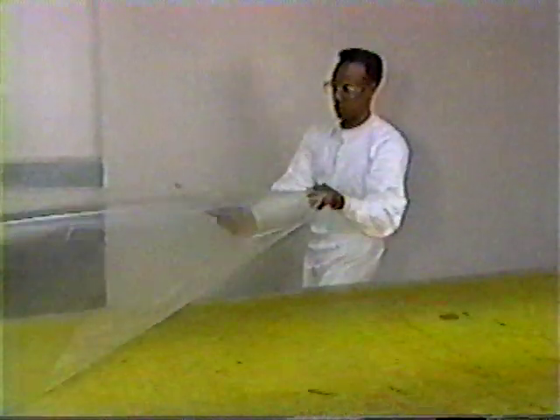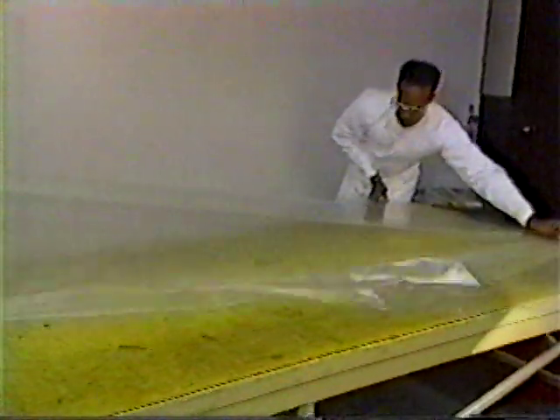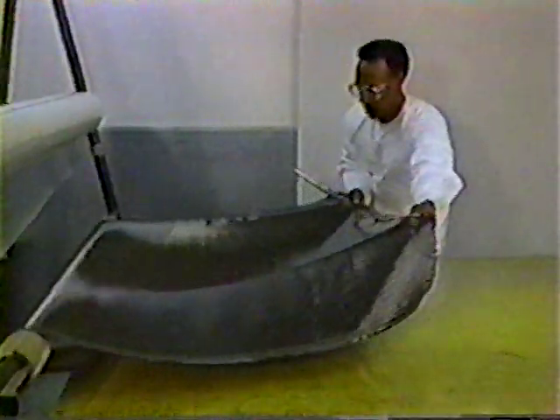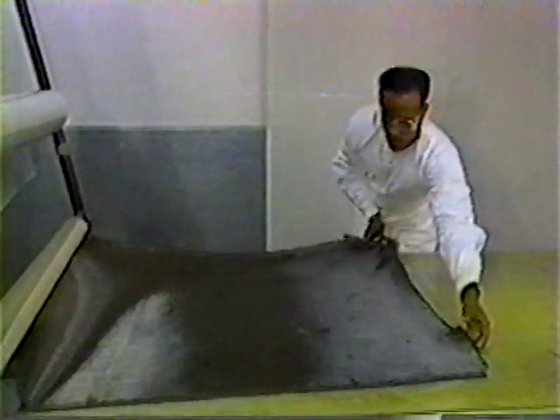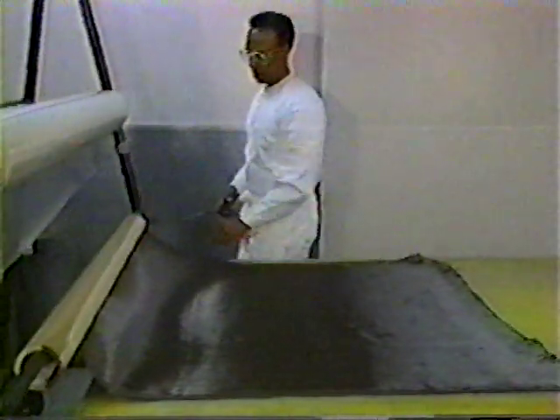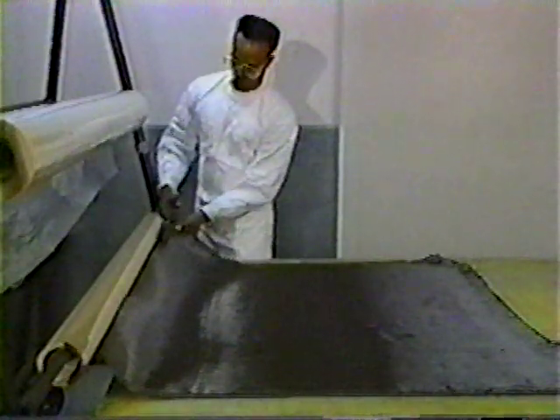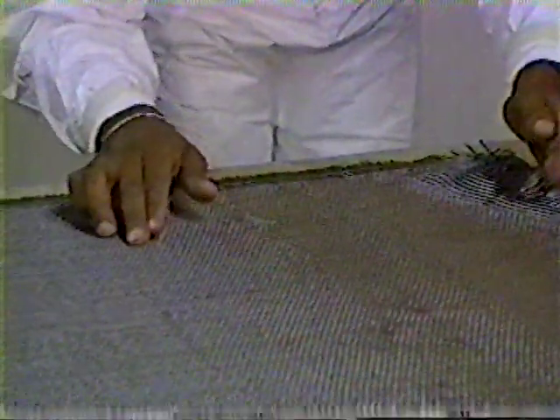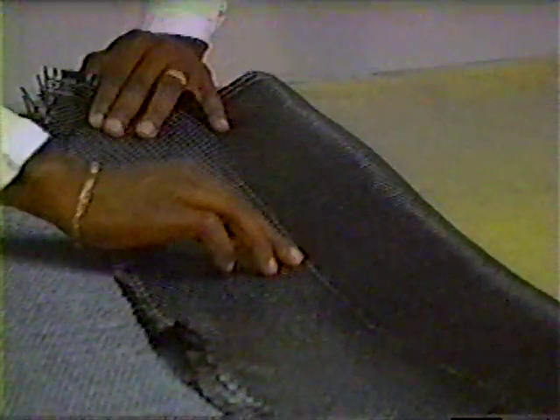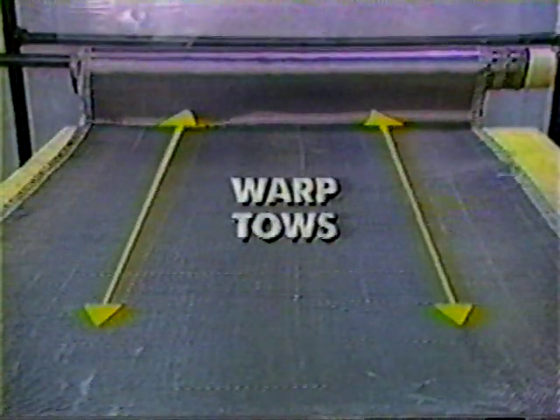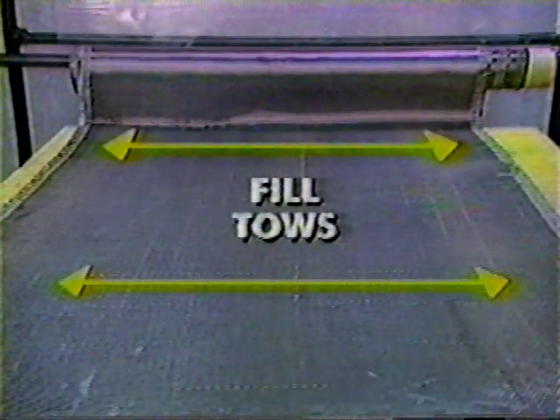Next, pull out a sheet of non-porous parting film large enough to cover the work table. Then, cover this with a sheet of graphite material that will be large enough for all the fill and repair plies needed to make the repair. Make certain to identify both the warp direction and warp face of the graphite material before applying the resin. The warp tows, or strands, will always run the length of the roll, while the fill tows, or strands, will always run the width of the roll.